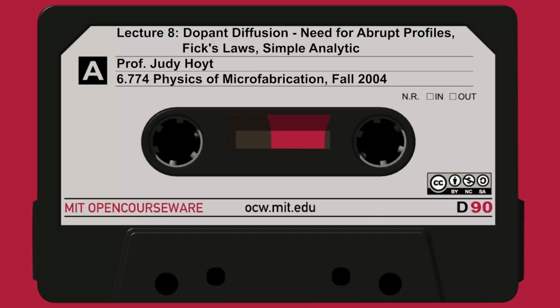You integrate that from 0 to xj. You can do that numerically for an arbitrary doping profile. The equation has actually already been integrated numerically for certain special analytic profiles, and we'll talk about those results later. So that's basically how we get from the doping profile to the electrical properties such as the sheet resistance or the resistance of a region.